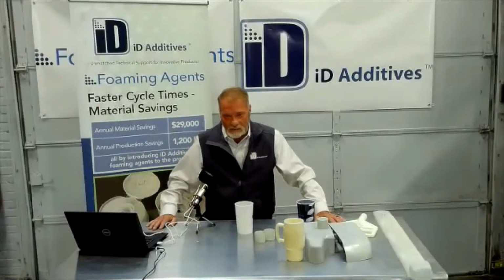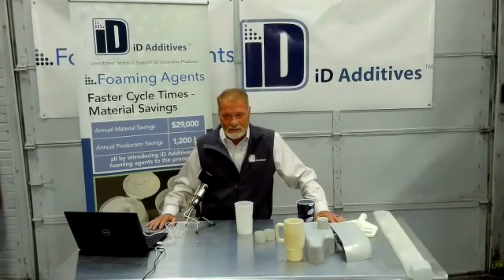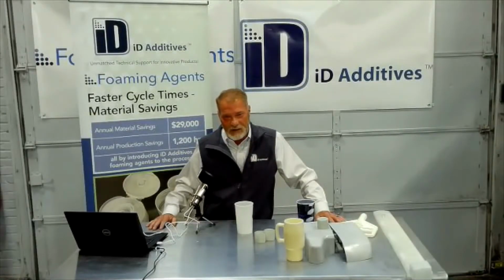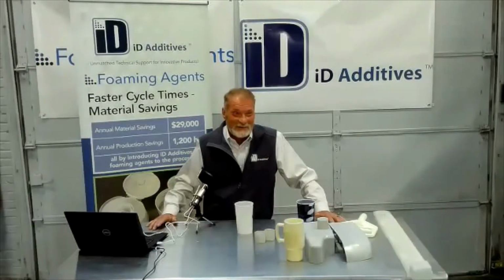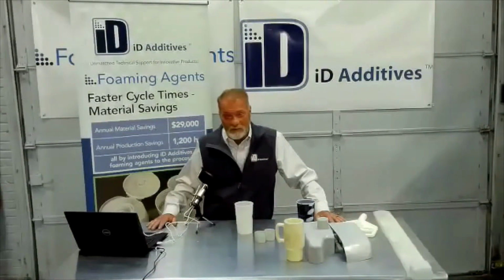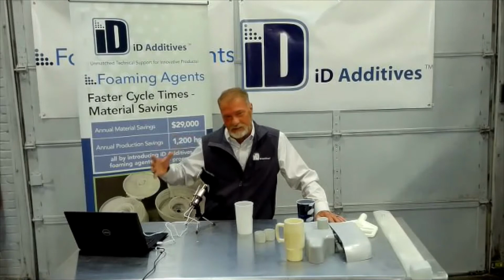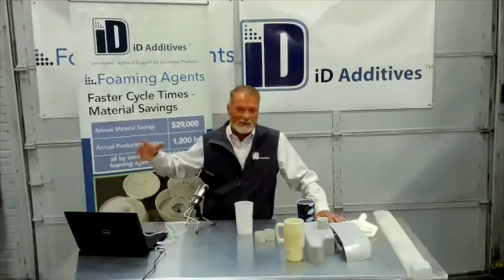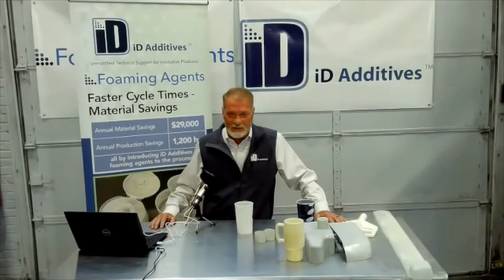So when it comes to reprocessed material or regrind, they foam a lot better than virgin material. And not sure why that is, but I know that if I'm running 100% regrind, it foams extremely well. I think mainly because it's seen a history of heat, so it breaks down a little bit, which makes it a little easier to foam. But yeah, definitely, we have customers run 100% regrind, and it foams beautifully for them. So definitely,